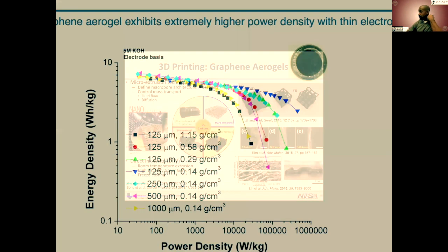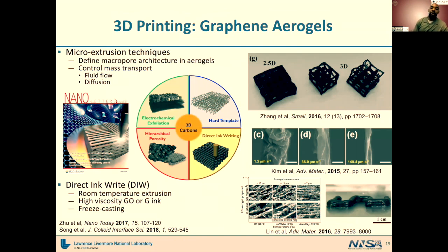So we chose to attack that problem using 3D printing. We believe that we can define the architecture of these aerogels. They're primarily made up of these very small, fine pores, which are difficult to navigate and are dominated by diffusion in terms of their transport. But if we can move to larger pores and really engineer what we call macro pores into the aerogels, we can then start to have more of a fluid flow transport regime, which allows us to have much faster mass transport.